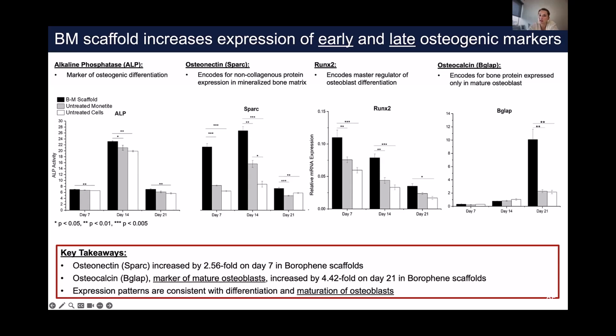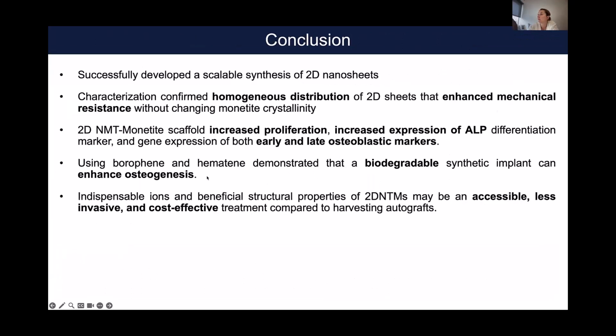So the conclusion for that first chapter is that we were able, first of all, to scale up the process to produce this 2D nanosheet. And I say that because it was not that easy. It's not that you just put the material in ultrasound and hope for the best. It's really difficult to get something without breaking up the nanosheet into small pieces. And it's not like electrocatalysis, where you just need a little amount. Here, you need a huge amount of material because you need to do your experiments in triplicate and you need to dope them as much as you can in your cement. So that was the first thing, and I think they did a very good job improving the synthesis technique for those two nanomaterials.